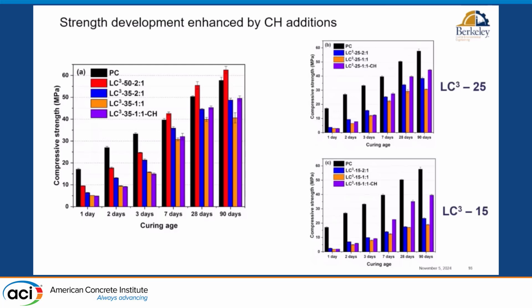But as we start going down in clinker content, you can see that the purple bars, which are the systems that are doped with calcium hydroxide, get significantly higher strength than the reference system. And in the case of LC315, we basically get double. And that doubling of strength compared to the control is coming from the carboaluminates. The system without the calcium hydroxide doesn't have the carboaluminates, the other one does. And this is more than irrefutable proof that these phases are contributing, as C-S-H and everybody else, to compressive strength.